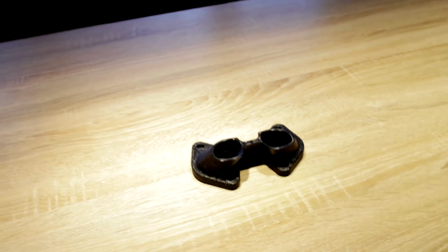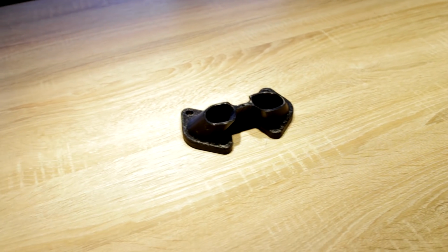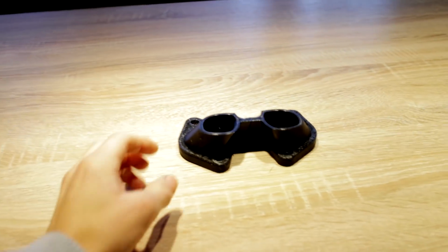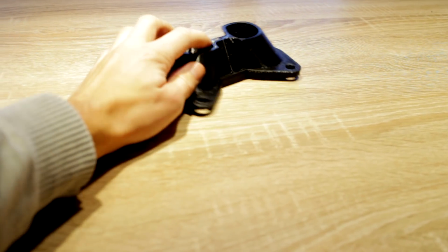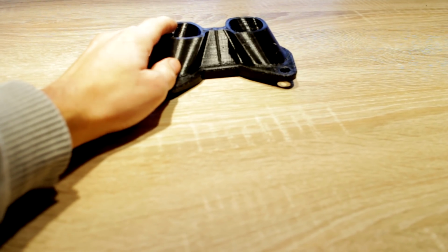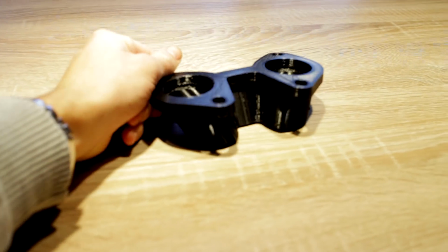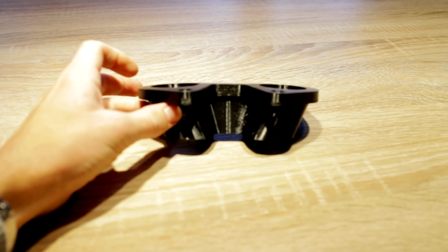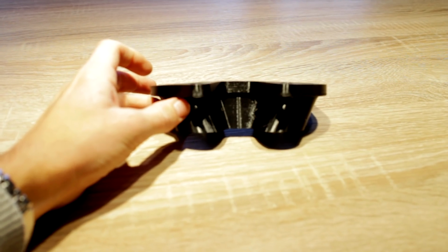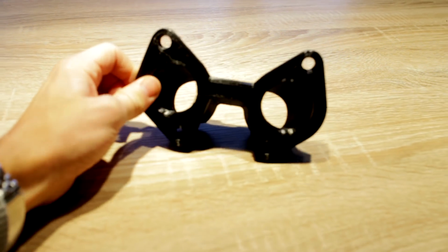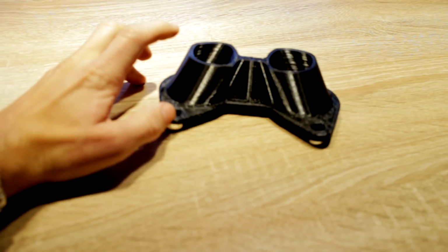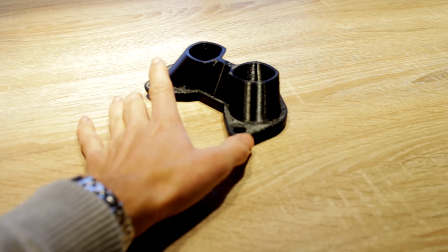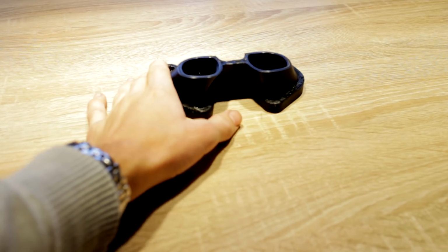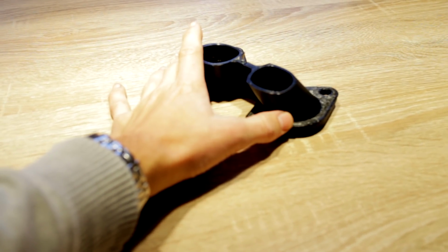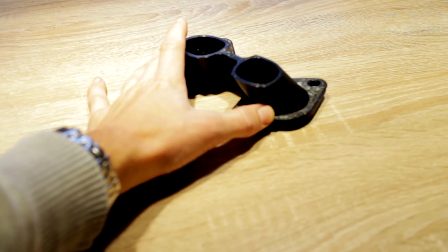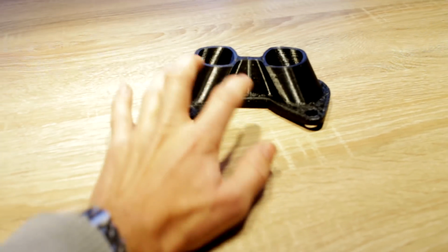So I was trying to 3D print the intake manifold and it went a little bit wrong. You can see it turned and it's not stable, and that's because the bottom has warped, and this has warped a lot. As you can see, it's completely crooked. This is the first time that this has happened to me, but this is also the first time that I'm printing this large footprint object in completely 100% infill, so it's completely solid, and this has caused a little bit of shrinkage.